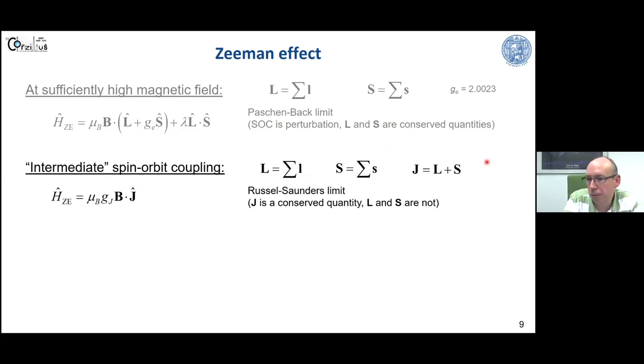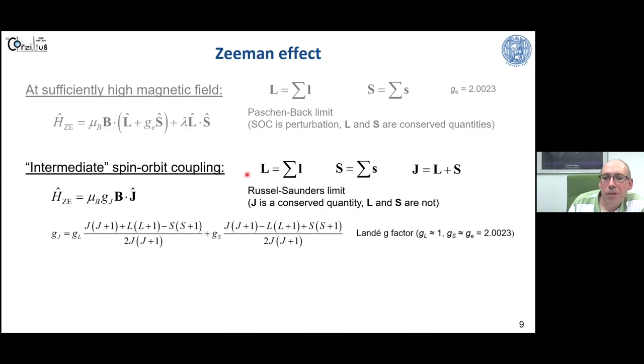This is what I've explained in the zero field limit and on the slide earlier. And this also has to happen practically when the spin orbit coupling is at least on the same order as the actual Zeeman energy. Now, J is a conserved quantity in this Russell-Saunders limit, and L and S are not. So orbital momentum can be interconverted into spin momentum and vice versa. However, the total angular momentum is always conserved. And in this case, we have to look at the Landé g factor. And this is given by this equation, which practically just adds the orbital contribution and the spin contribution to a total g factor.